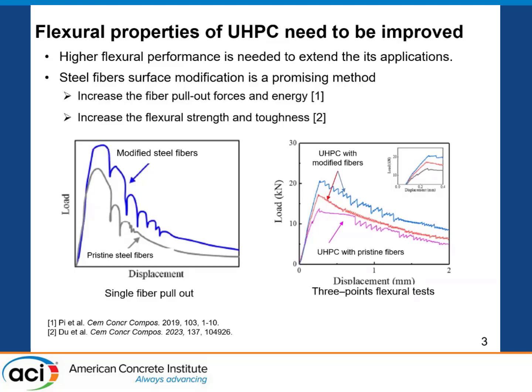The general background problem is the need to further improve the flexural properties of UHPC for extended applications. There are many ways to improve flexural properties, such as controlling the rheology for better dispersion and orientation of the fibers, or using multi-scale fiber reinforcement. One very effective and promising method is to coat the steel fibers, modifying the fiber surfaces, because it can increase the fiber pullout force and energy, as you can see in some of the literature results, and thus help improve flexural strength and toughness.